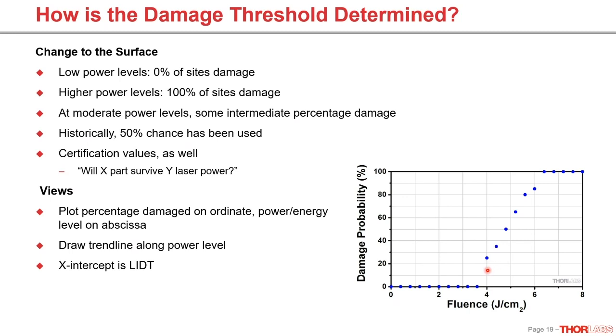As you modulate your power levels, you will eventually see some power levels where a percentage of your sites are damaging. If you test 10 or 100 sites, you'll get something in here where maybe 25% of your sites damage. Once you get to those intermediate power levels, you're going to want to get a few of those so you can get a curve like that. Then you plot them like this and draw a trend line basically through the damaged sites. Where that trend line intersects your x-axis is typically treated as the damage threshold. Usually in a curve like this, that's going to be relatively close to the highest number you were able to test with 0% damage. Sometimes you may want to build in a safety factor and cut some percentage off of that number. But that is typically what is reported by most testing houses.